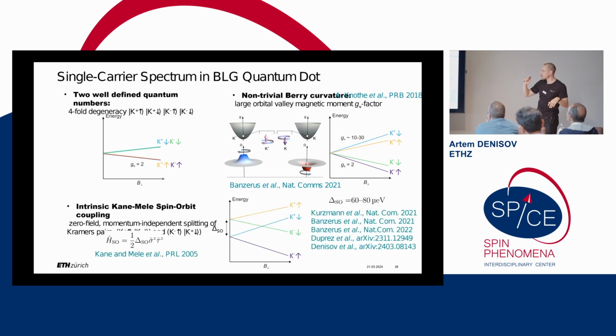However, it's not the end of the story, because also due to the hexagonal symmetry, there is an intrinsic Kane-Mele spin-orbit coupling, which is a momentum-independent spin-orbit coupling, which just splits two Kramers pairs at zero magnetic field. Like it splits this four-fold state into doublets. And each doublet is called a Kramers pair, the two states which are related by time reversal symmetry, meaning that in order to go from one state to another, you need to flip not only the spin, but valley too. And the splitting was experimentally measured many, many times, directly and indirectly, and we know very well that it's something between 60 and 80 micro electron volts in bilayer graphene.